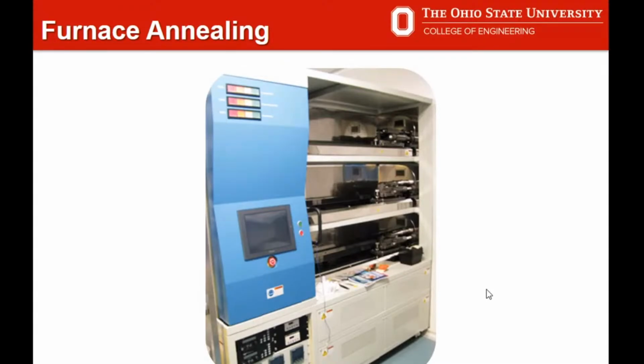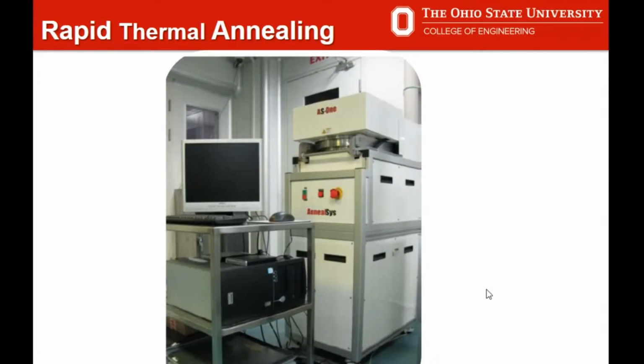And at the same time, the biggest advantage of furnace annealing, I'm sorry, it's not an advantage, it's actually a disadvantage compared to your rapid thermal annealing. That is, you could go for say 8 hours or 10 hours or a whole day for annealing. So it would take a lot of time compared to rapid thermal annealing. If you are using rapid thermal annealing, you could end up within 20 or 25 minutes, including everything. But in case of furnace annealing, you have to wait maybe 24 hours or maybe more than that, depending upon the criteria you are choosing. So yeah, rapid thermal annealing, I think I've vividly described in my previous slides. So these are the differences between the rapid thermal annealing and furnace annealing.